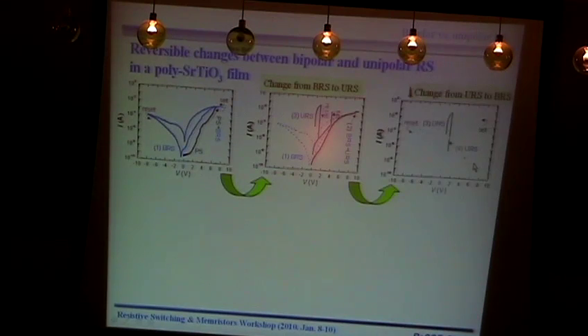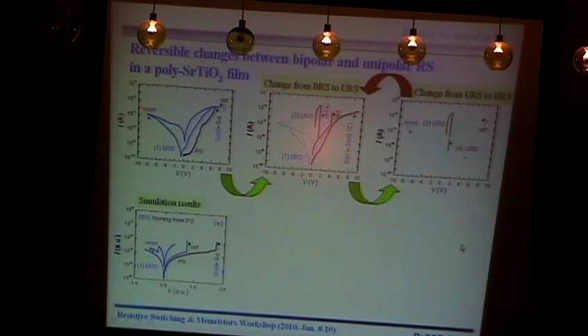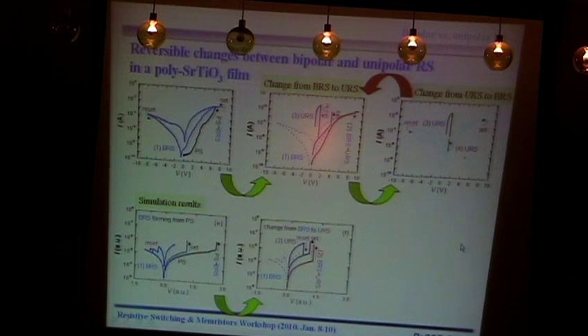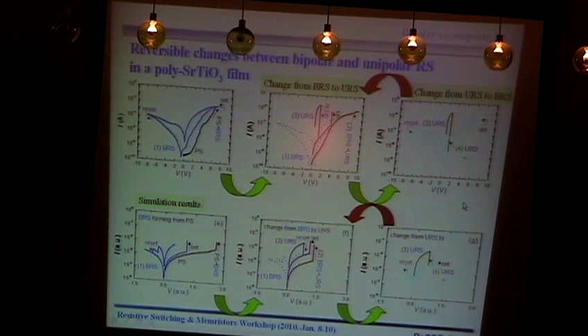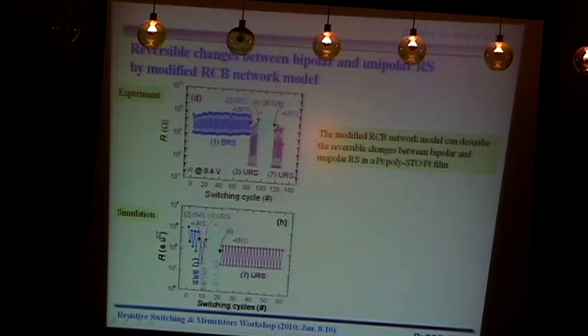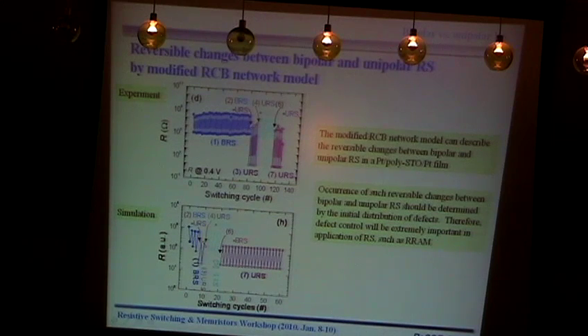So what we have done is that this is the experiment I already described to you. So with a particular defect configuration, we can actually find out a solution which can actually do the same thing like this. So it changes from the bipolar to unipolar to bipolar to unipolar, and so on. So this is the experimental data. This is the simulation data, which can actually mimic exactly what is happening in our experiment. So our modified RCB network model can describe the reversible changes between the bipolar and unipolar resistance switching quite well. And the occurrence of such kind of reversible changes to resistance switching should be determined by the initial configuration, initial distribution of the defect. So it is very important to control the defect in order to use the RRAM devices.